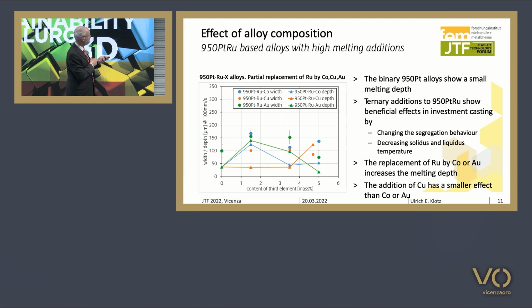On the left side there is the platinum ruthenium alloy, and on the right side there is the platinum copper, platinum cobalt, platinum gold alloy. If you look at the triangles, the depth is not affected by copper, but we see an increased depth if we add some cobalt or gold to this alloy.